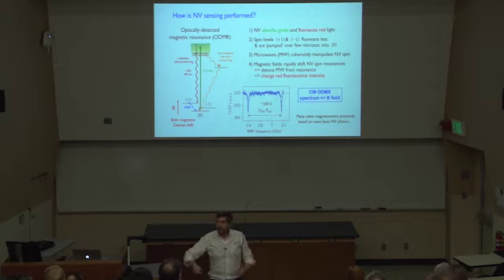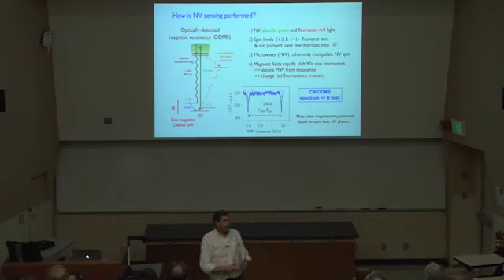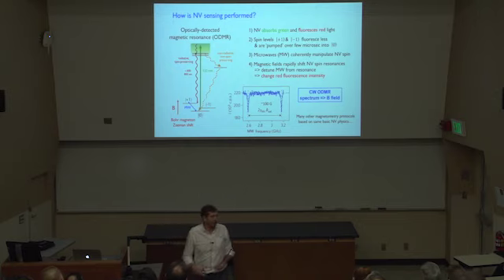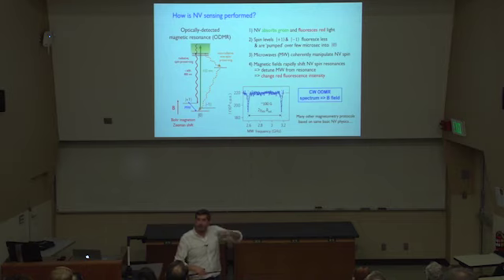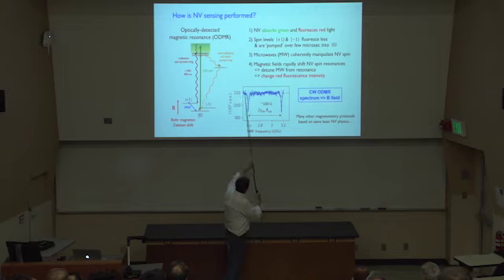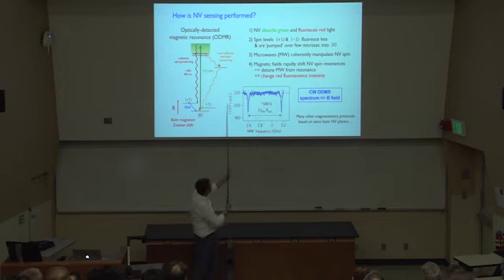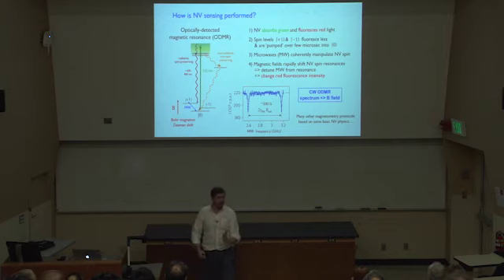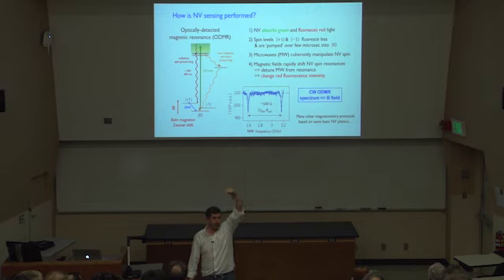The green light is trying to take the NV back to ms equals 0. The resonant microwaves are trying to drive the NV to either plus 1 or minus 1, where the fluorescence rate is lower on average. And of course, this is averaging over many runs. You're just continually illuminating and measuring and measuring. So you say, if I know what the gyromagnetic ratio of the NV is, and I can measure these positions very precisely, I can get out what that magnetic field is from that splitting. And what things matter? The larger the intensity, the better. The deeper the trough, the better the contrast as a function of magnetic field or microwaves. The narrower that transition, the sharper and deeper that line, the better in terms of determining the magnetic fields. You'd like a really narrow, sharp line, and that splitting would tell you what the magnetic field is.